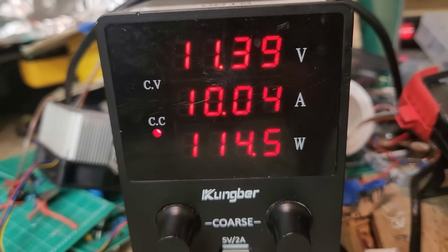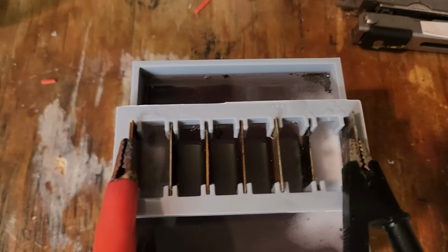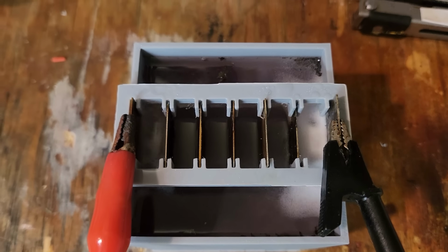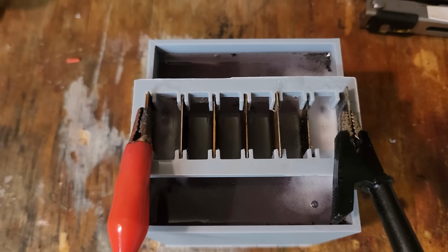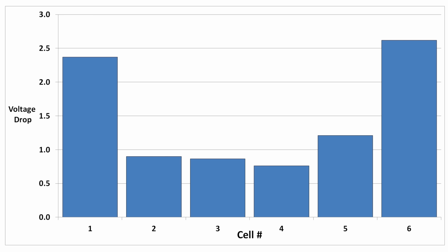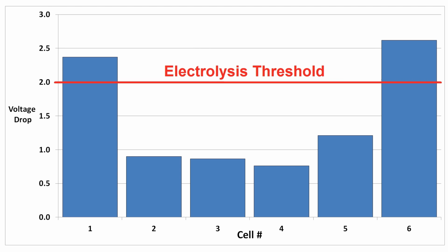At 11.4 volts, we've got a whole 10 amps, but look at the gas production. It's only on the outer plates and none of the inner cells are producing anything. If I measure each cell individually, we can see the problem. On the outer cells, we've got a voltage drop of around 2.5 volts, but on the inner cells, they're all far below the threshold for electrolysis because the current is just going around them. As it currently stands, this stack is just generating mostly heat. Now let's see what happens if I put barriers between the cells.